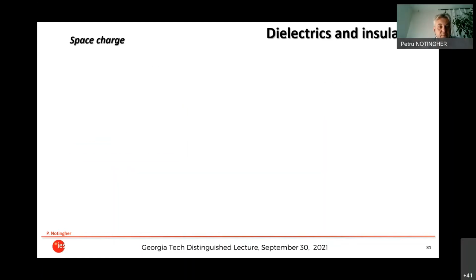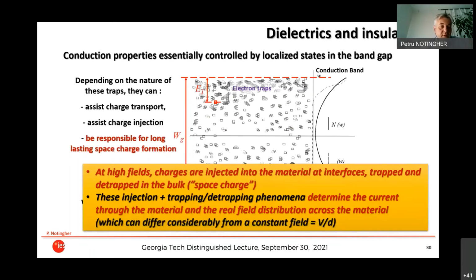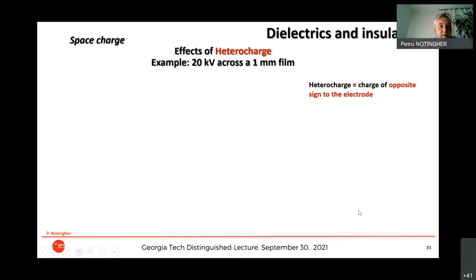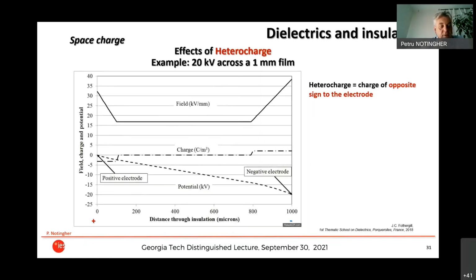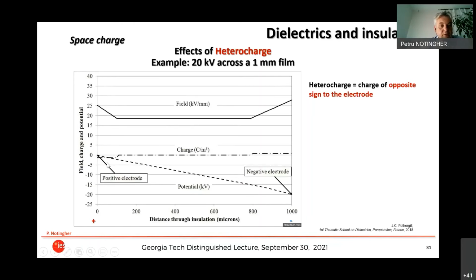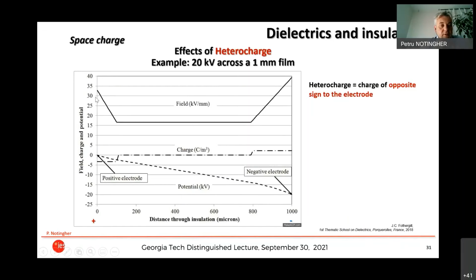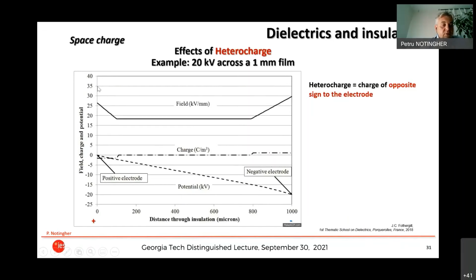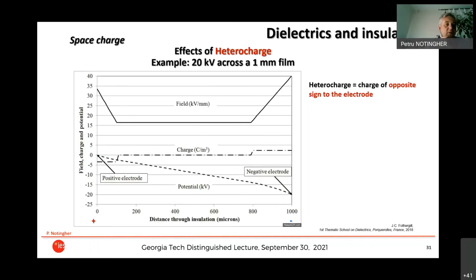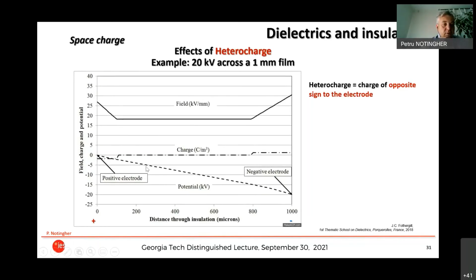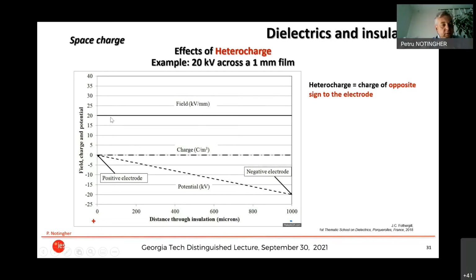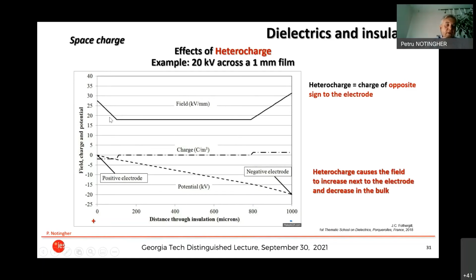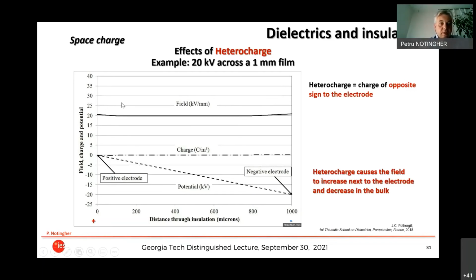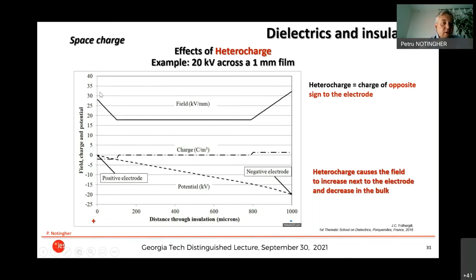So what are the effects of this space charge? If you inject charge and if the charge is trapped and it stays in the traps, then you'll have an enhancement of the field, and this can be very spectacular. For instance, if you have heterocharge, that means charge that has a sign opposite to the electrode. Like here, you increase the charge at electrodes, so you increase a lot the field at the electrode. So instead of having 20 kilovolt per millimeter, you will go to 40. It's exactly the same thing that you have when you polarize the material. But if you inject the charge over an important thickness, this field will be high over an important thickness. So this can be very detrimental to the material, because instead of having 20 kilovolt per millimeter, you have 35 or 40.